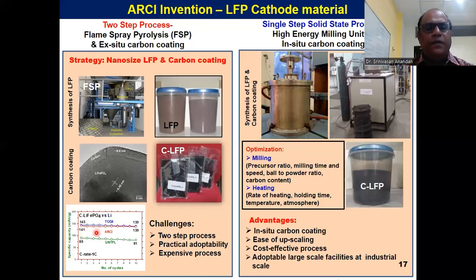If you look at the ARCI material, it is able to deliver 141 milliampere hour per gram, which is close to the capacity of one of the commercial materials which we obtained from TODA. And the capacity of the material is much better than the other commercial material, which shows only 89 milliampere hour per gram. Even though we are able to synthesize the material which is at par with the commercial material performance, there are challenges when using the two-step process. It is an expensive process, and practical adaptability is very challenging. So we realized the importance of using a single step process for making carbon coated LiFePO4 in a single step.